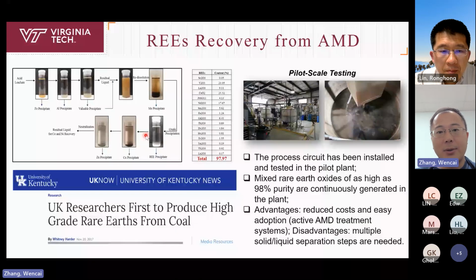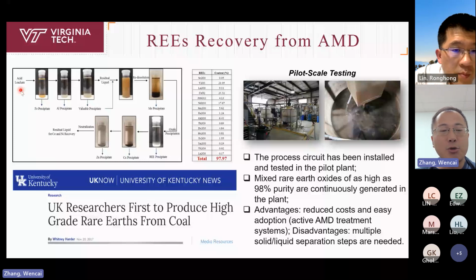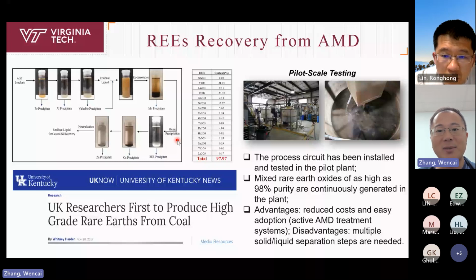So based on this method, as you can see here, this is a staged precipitation process. We collect the preconcentrates of the rare earths and redissolve the precipitates. We get a solution with a high rare earth content, and then we did some oxalic acid precipitation tests. With one stage of oxalic precipitation, you can generate a rare earth concentrate with around 98% purity, which is very encouraging. As I mentioned, the feedstock of the acid mine drainage only contains around 6 ppm of rare earth elements. But after this simple process, you can get a precipitate that contains 98% rare earth. So this is a huge enrichment of rare earth through this process.